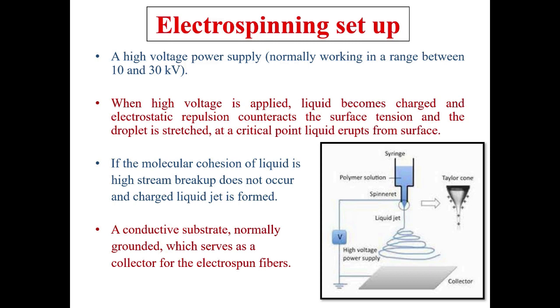In the electrospinning setup, this is the schematic form. Here we use the high voltage power supply controller. The connectors are connected to the needle, and the solution is put into the syringe. There is a compressor which pushes the solution, pumping it through the needle. Then fibers are collected over the collector plate. It is a conductive substrate. Over that conductive substrate, nanofibers can be collected, and they form the Taylor cone system. When the solution comes from the needle, there is a formation of the Taylor cone. That cone is called a Taylor cone, which is positively charged, and because of that, the conductive substrate is essential for the collection of the fiber.